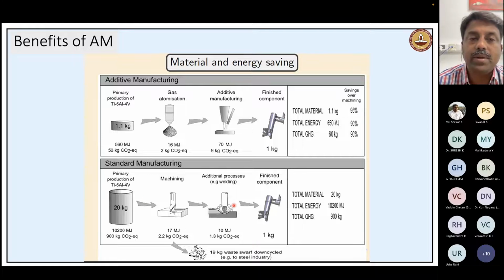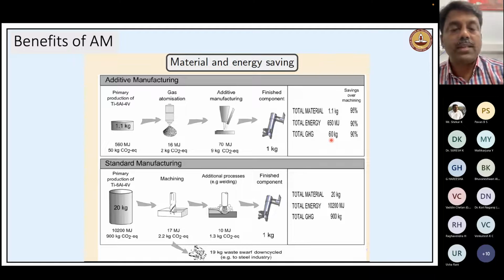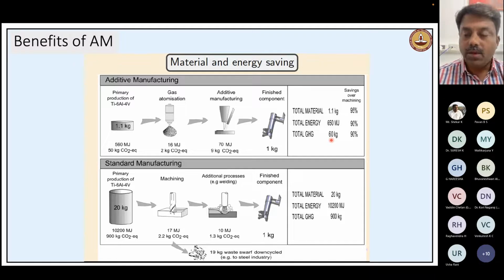As compared to the standard manufacturing process, suppose you want to print by additive manufacturing, say for example a powder bed process. We start with about 1.1 kilogram of billet, we atomize, do printing, and then get the part. The amount of energy you spend is not even about 600 megajoules, and you save about 95% of material. We also save a large amount of greenhouse gas emission during this process. So the material and energy saving is one of the biggest advantages of moving from conventional manufacturing to additive manufacturing. So what are the other benefits?